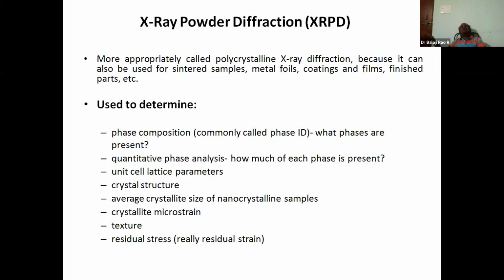Earlier, people did this because there was no other kind of characterization to estimate, around 50 or 40 years ago. But nowadays, there are SEM, TEM, AFM, STM, and other sensitive characterizations where the resolution of the compound goes from 2 nanometers to 0.2 nanometers, related to HRTEM values. Therefore, friends, whatever data and information you observe from the XRD should be matched with the SEM results, TEM results, or HRTEM if possible. The results obtained from the XRD of your sample should match some of the parameters with visible characterizations such as SEM, TEM, and STM, so that you compare together how much error is there.